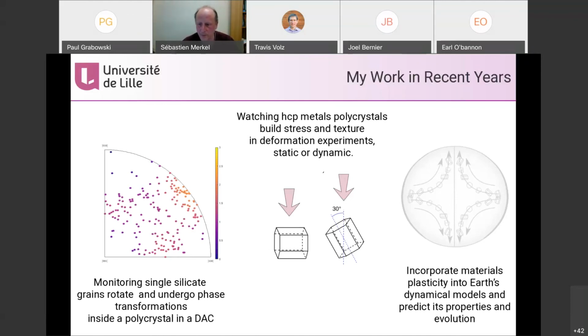So, out of the 4 experiments, 4 conditions, we have 2 where we overcame the yield strength barrier and 2 where we did not. I can tell you it's not a pressure effect. One set of experiments at 20 GPa, we did go over it, and the other 2 are in between. So it's not because we were at low pressure versus high pressure.